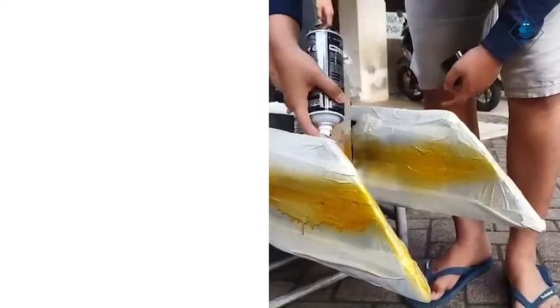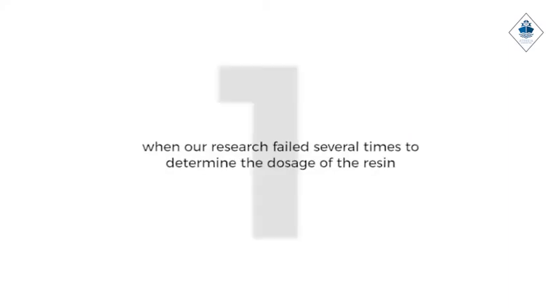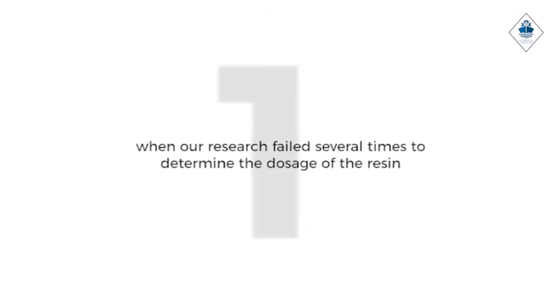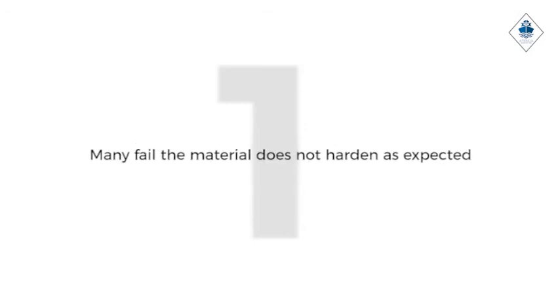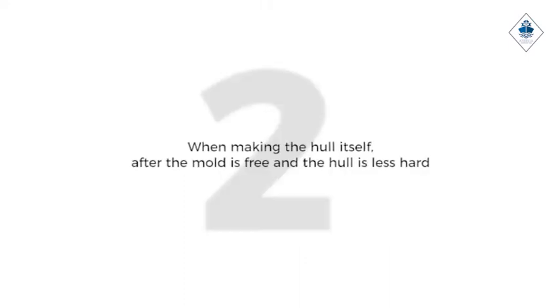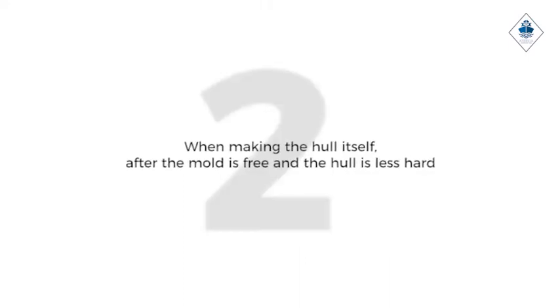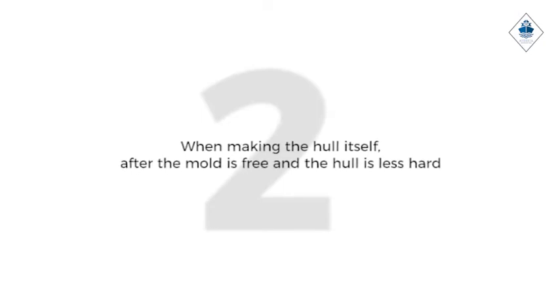For the ship that we make, there are several obstacles that we get during the work on the ship. First, our research failed several times to determine the dosage of the resin, mainly the material did not harden as expected. Second, when making the hull itself, after the mold is free and the hull is less hard, in the end, we give the hull fixture to make it harder.